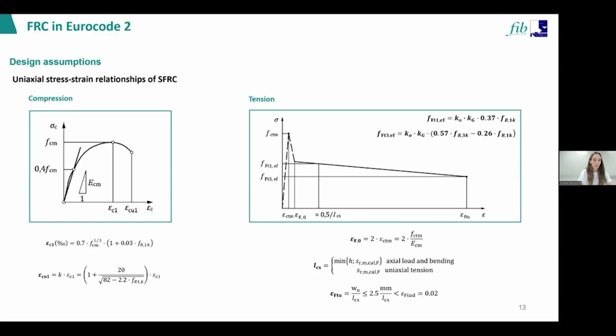So now let's continue with the constitutive law for the materials. In compression, what Annex L proposes is that the constitutive law remains relatively similar to that of the plain concrete, although fibers contribute to increasing the ductility and energy absorption capacity of the material. For this reason, there are modifications in the compressive strain corresponding to the peak compressive stress and the ultimate compressive strain. But the main difference appears in tension.